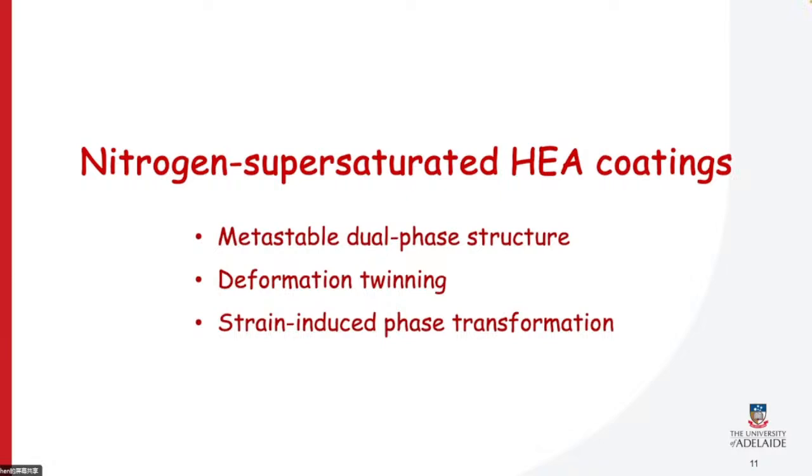The reason for doing that is, in addition to phase metastability, which will give us a dual-phase structure, deformation twinning, and phase transformation, we will also benefit from the massive solid solution strengthening caused by high nitrogen intake.